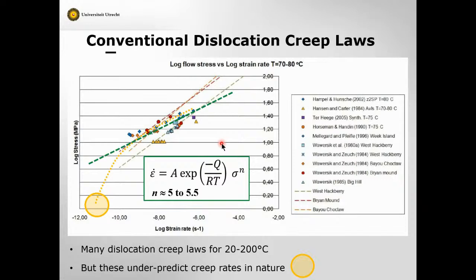There is a very noticeable problem for somebody who's familiar with salt in its geological environment, and that is that if you extrapolate this lab data, then it does not explain flow rates that you can see in nature, or in borehole closure rates, for example, or in borehole deformation shearing rates, which can be as high as 10 to the minus 11, or perhaps 1 or 2 orders of magnitude lower. Extrapolating this doesn't really explain the behavior of salt in nature.